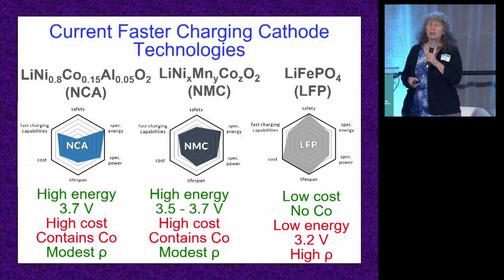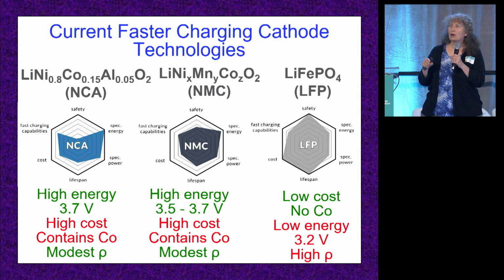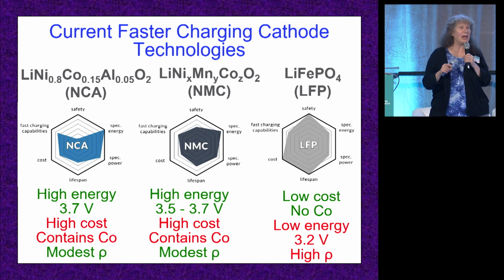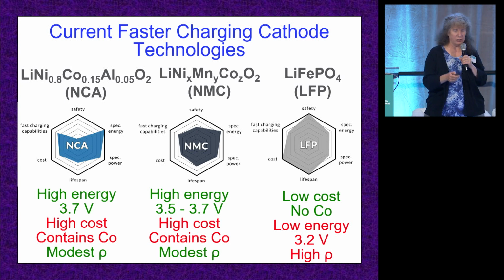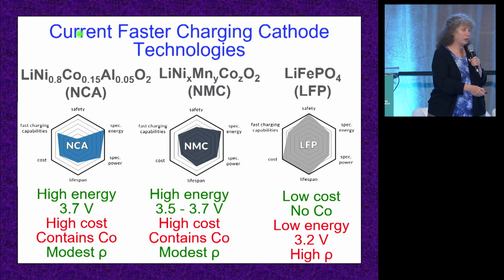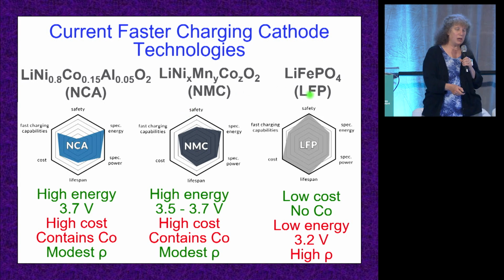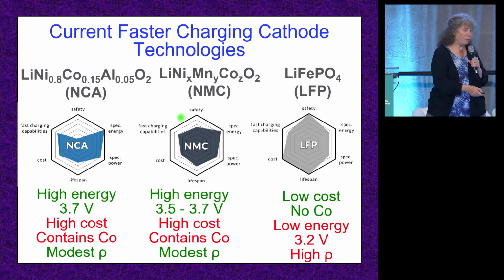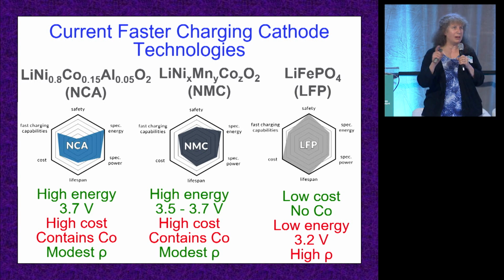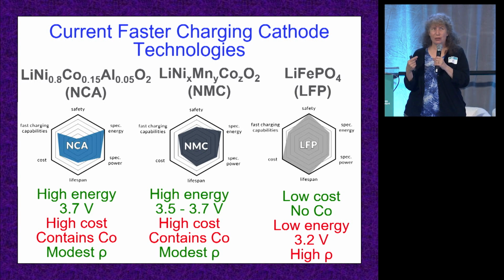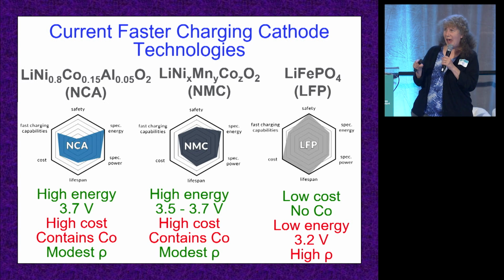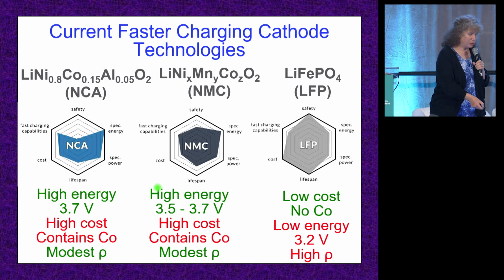So if you look at the current technology, there's a million different kinds of batteries out there. They're all the same inside. For the faster charging systems, they have three different possible cathodes, and two of them are almost the same. There's a lithium nickel cobalt aluminum oxide called NCA, a lithium nickel manganese cobalt oxide called NMC, and a lithium iron phosphate. So these two are very similar. They're both pretty high energy systems. They are high voltage. We're going to talk about capacity and voltage. The capacity times the voltage is the energy that you store. So you need high capacity and high voltage. So these are high voltage systems.